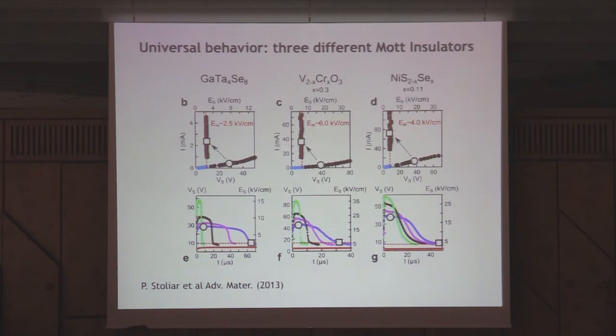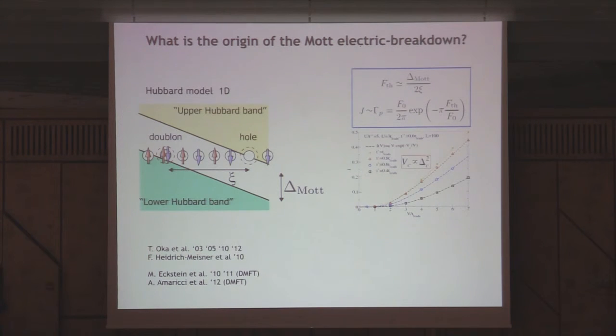So the experimental group in Nantes did a systematic study in these three systems, and all show an amazingly similar behavior. So here is the data that I showed you before with this series of voltage versus time transitions. This is in V2O3. Actually, it's not V2O3. V2O3 is metallic. You have to put some chrome in order to make it insulator. So this is chrome. Same thing for nickel sulfur selenide. And you see that this qualitatively resembles the same. So it's amazing universal behavior. Moreover, if you look at the threshold fields above which you start getting a transition, you see that all are in the kilovolt per centimeter regime, and the times involved are of the order of microseconds. And of course, with higher voltage, you can make it quicker. Okay, so what is the origin of this universal behavior?